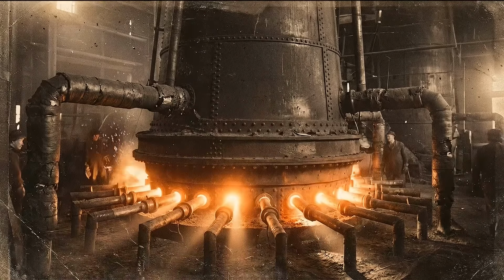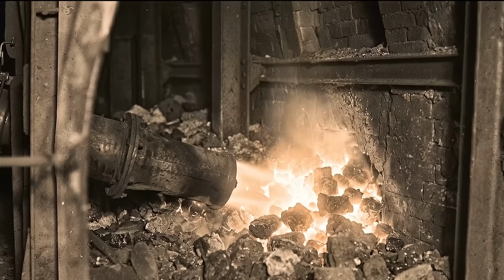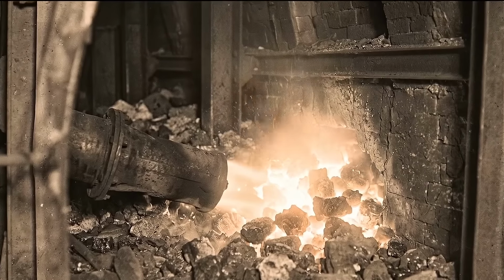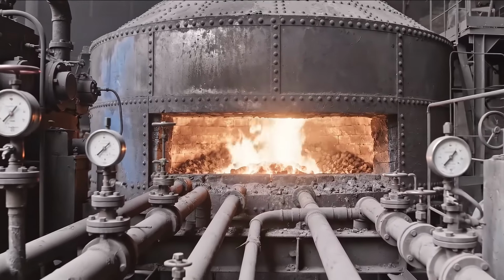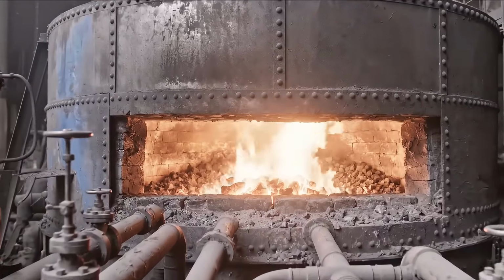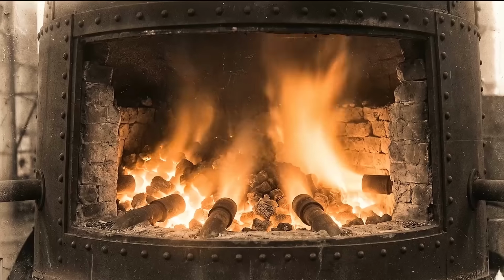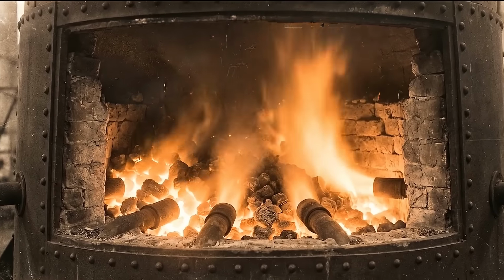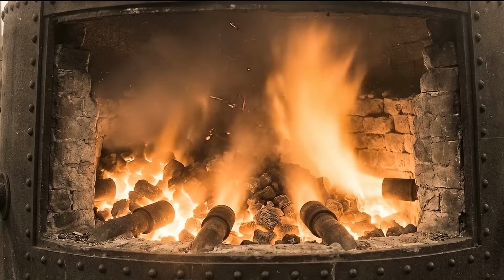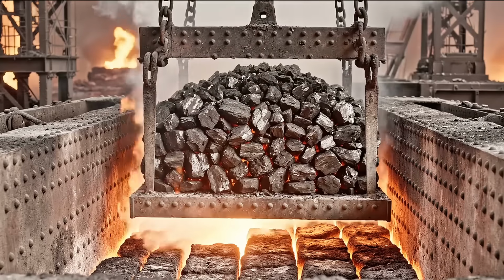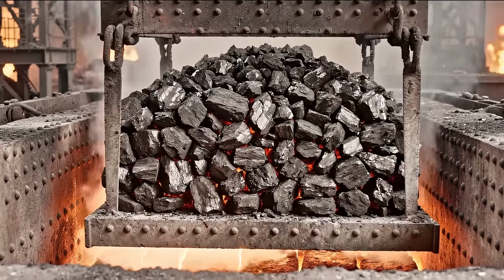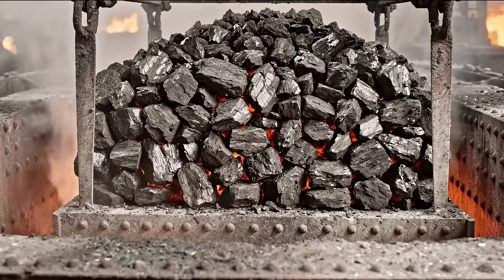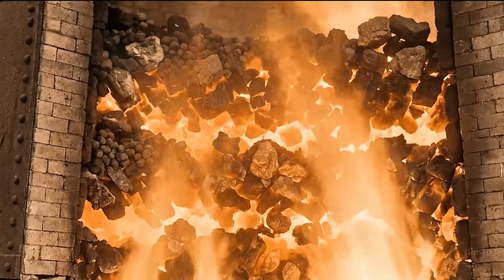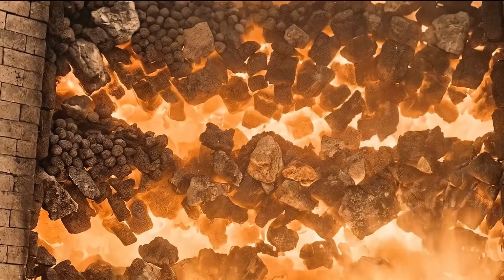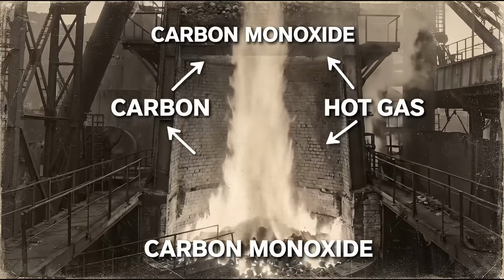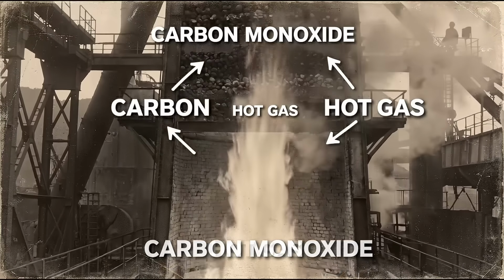That is where the name blast furnace comes from. The blast. When that superheated air hits the coke at the bottom of the furnace, the temperature in the combustion zone spikes to between 1800 and 2200 degrees Celsius. The coke ignites and reacts with the oxygen in the blast to produce carbon dioxide. But the furnace is so hot and so packed with carbon that the carbon dioxide immediately reacts with more coke and converts into carbon monoxide gas. This is the critical moment. That carbon monoxide is the real workhorse of the entire process.